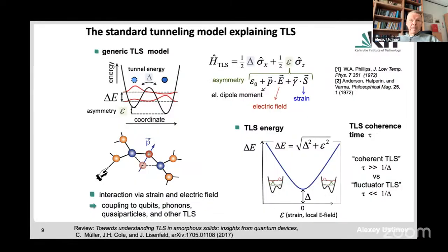The energy scale of an ion of the lattice in a solid is in the electron volt range. However, the phenomena which were observed by experimentalists at that time, looking at glasses, were in the micro electron volt range. They were actually observed at temperatures well below 1 Kelvin, which would correspond to a characteristic photon frequency of about 20 gigahertz. So it was well below 20 gigahertz. That means that the barrier which you have is very narrow, but could also be very high. And the only process which can happen, with such steep walls rising on both sides of this barrier, could be tunneling. So the Hamiltonian of the system, as shown here, is written as a sum of two terms.